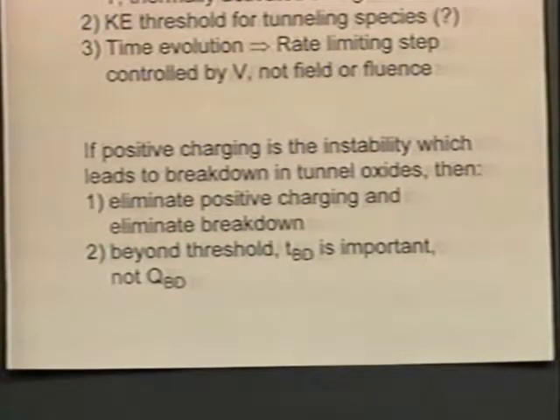But breakdown, if it's related to positive charging, it's just something that evolves in time. You sit for a certain amount of time and then you have the breakdown, if that relationship is true. I'm just whetting your appetite. So what you would measure if you're measuring QBD is an exponential increase in QBD with thickness. But the reason for that is because breakdown itself is related to this positive charging, which is something that just evolves in time. And you're trying to ascribe charge onto a process that charge doesn't control at all.